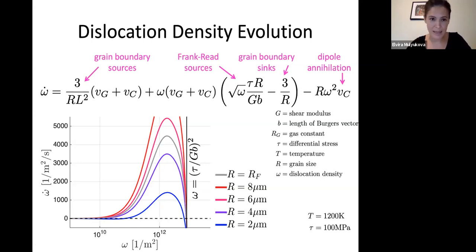Actually, no, I'm sorry. I think I may not have explained that. In order to bow out the dislocation, there needs to be some minimum amount of stress that is resolved on the plane of that dislocation. That minimum stress depends on the distance between the pinning points. You can think of bowing out the dislocation as kind of like bending a beam, and it's easier the longer the beam is. So there needs to be a minimum stress in order to operate this Frank-Read source.